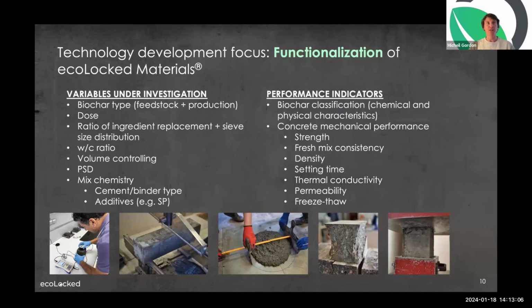When it enters a concrete mix, it immediately starts absorbing the free water in the mix, leading to a stiffer mix. It's harder to work with and it cures faster, and this can have its benefits. But in the case of ready mix, when you're pumping concrete, it can have catastrophic effects. For example, if the concrete gets poured into a truck and then you can't get it out. So it's very important. You might think it's easy, you just add more water. Well, adding more water leads to a reduction in compressive strength quite quickly, and there's a threshold there.